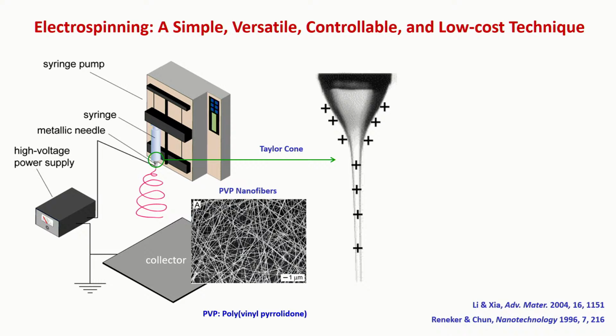Electrospinning is kind of a simple technique. It has been around for more than 100 years, probably you know it. The idea is simple. You just take a polymer solution, you put it in a syringe, and when the polymer solution comes out from this metallic needle, of course, you are going to have a droplet, more or less spherical shape, right, because of surface tension confinement. However, if you apply high voltage to this needle, that needle will be able to inject charges on the surface of the liquid droplet, and eventually you are going to create a very strong repulsion on the surface. So that will lead to the formation of a liquid jet due to the electrostatic repulsion from these charges.